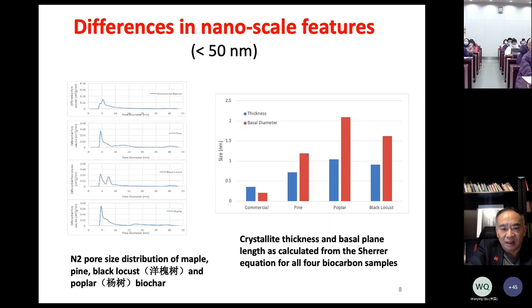And there are also differences in terms of porous structure. In this case, we're talking about pores smaller than 50 nanometers. This is from BET analysis, showing pore distributions of maple, pine, black locust, and poplar biochar. What I want to show here is that with different wood precursors, the micropores, which are less than, let's say, 20 nanometers, can be different.